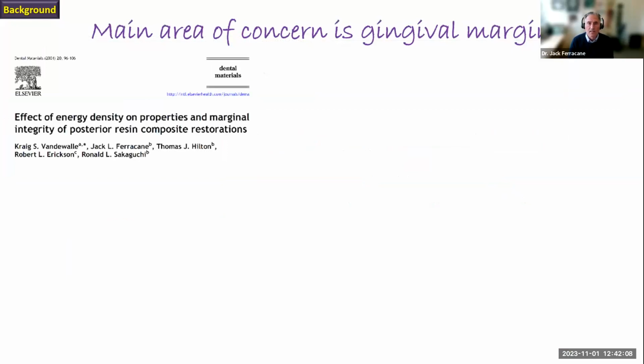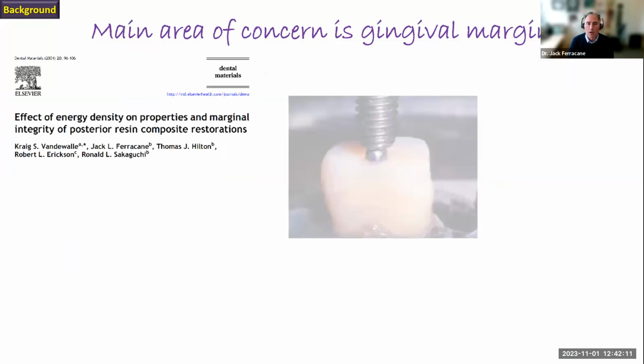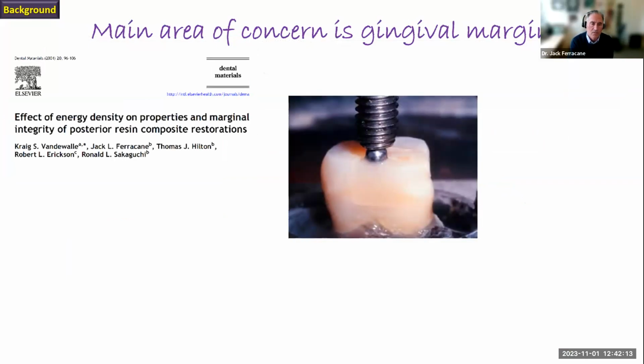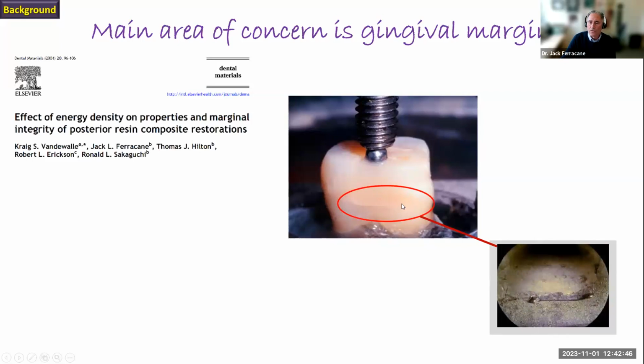So as again, we said, the main area of concern is the gingival margin. And we did a study years ago. Craig Vandewalle did this for his master's thesis while he was in the Air Force, with Tom Hilton and Ron Sakaguchi, Bob Erickson, and I. They basically placed class 2 slot prep restorations, embedded a ball bearing in them so that we could thermal cycle these materials, we could mechanically load these restorations, and we could soak them in water for various periods of time. And what he wanted to determine was how much light energy we have to provide to keep this gingival margin intact during all this activity.